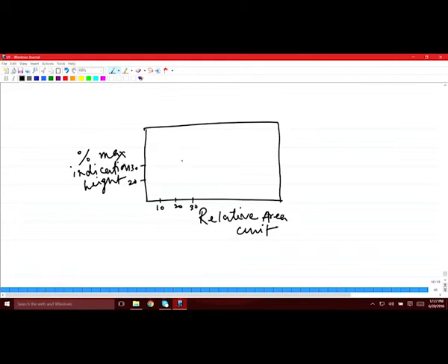It was somewhere around here. So, this is your first data point, which is 25, 33, because we have plotted in terms of percentage in the y axis. So, that is 33% in this case, or 1/3, and the x axis is the relative area, which is the square of the number of the block. This was for number 5 block, which means it is 25.